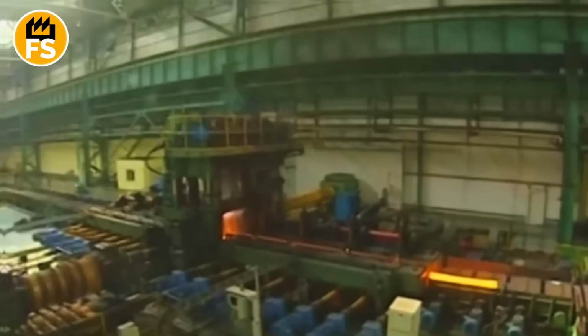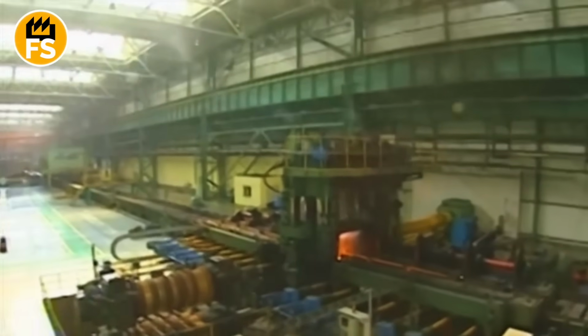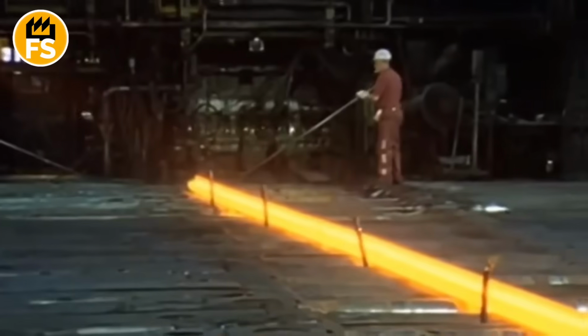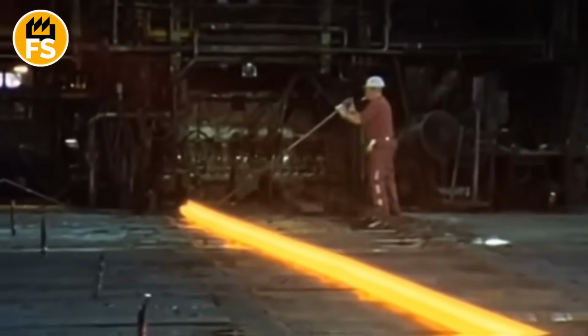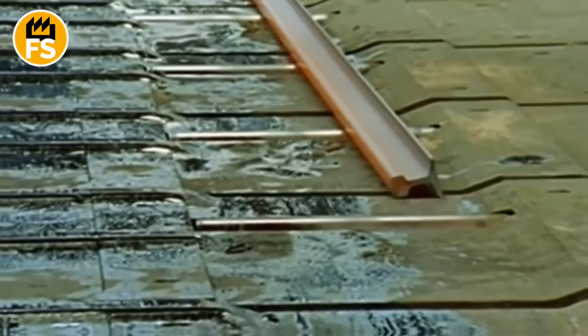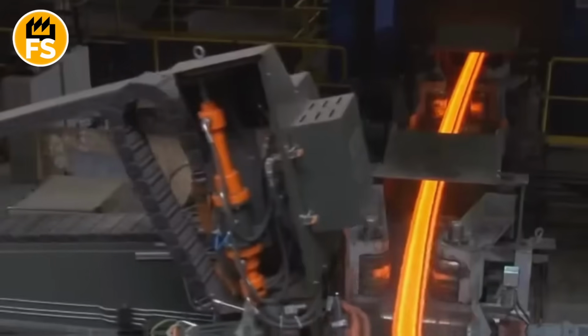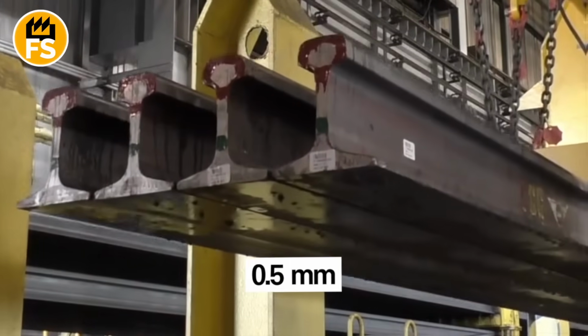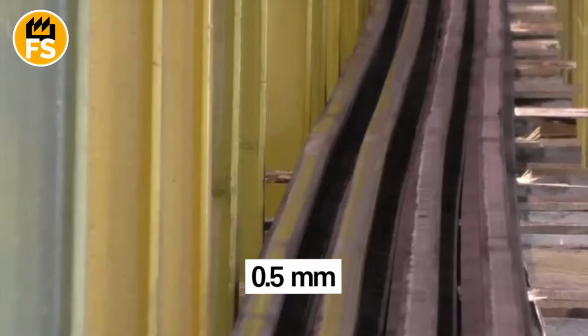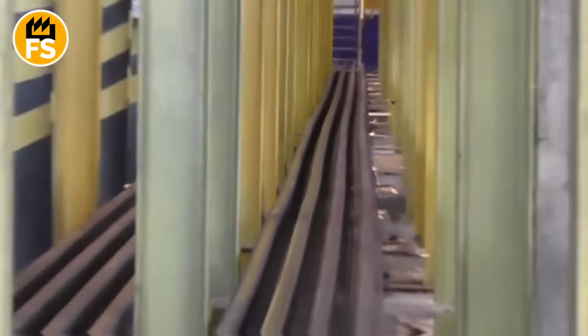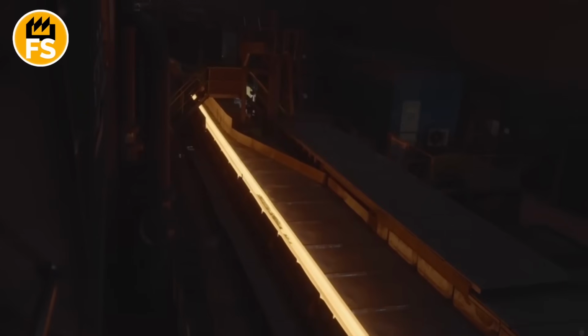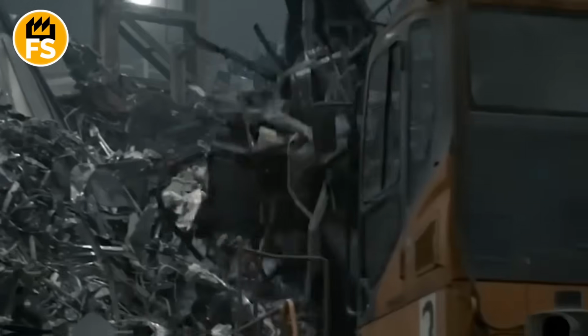And by the 10th pass, the vertical web section is taking shape. And finally, after the 22nd pass, you've got the complete rail profile with the base that'll get bolted down to the railroad ties. The crazy thing is that this entire rail shape has to be accurate within 0.5 millimeters, which is literally half the thickness of a dime, across all 39 feet of glowing steel, because if it's off by even 1 millimeter, the whole thing becomes scrap metal, and 12 tons of work goes to waste.